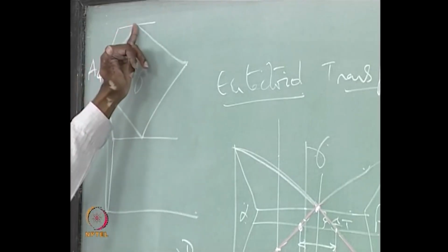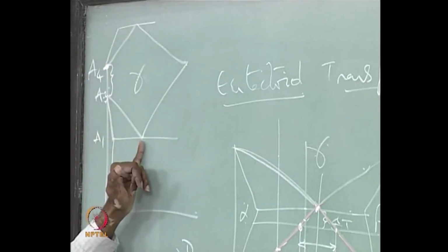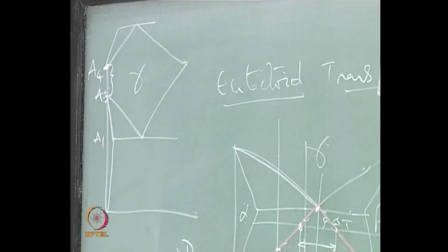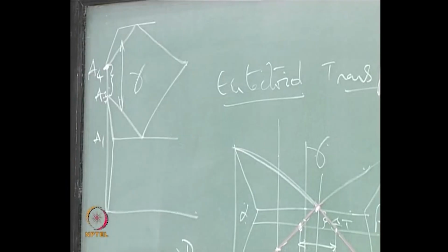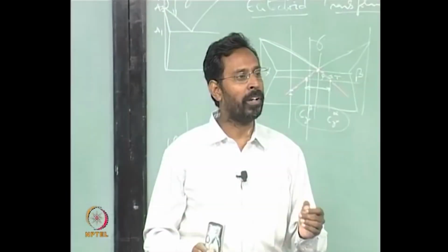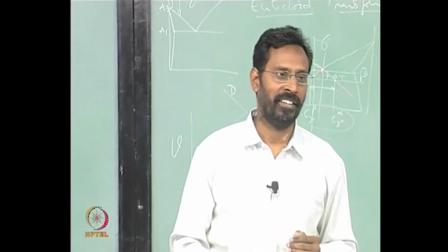Of course this is 0.18, this is 0.8, so there is a scale difference. Once I know that these two are increasing, it tells you that this field is increasing, and that means whenever a phase field expands, that particular element stabilizes that structure.